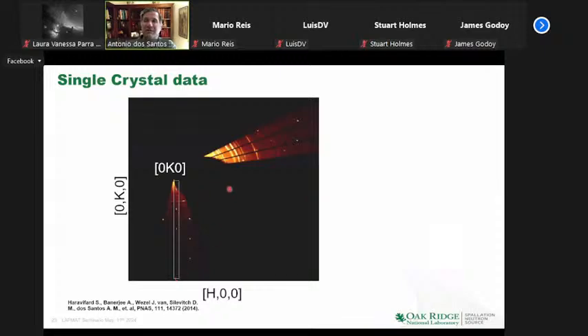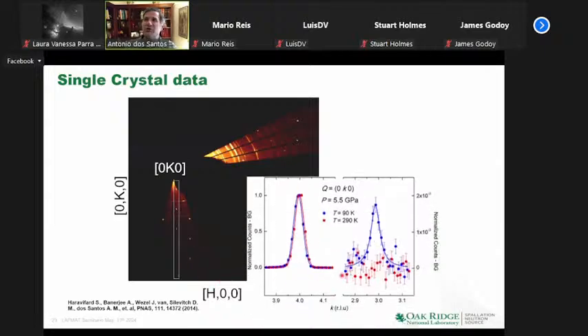Now, this pressure cell only allows in-plane scattering. So all you have is this HK plane, but you can see that in single crystal, every spot shows up and is resolved. And this is the advantage of time of flight neutrons: this is a single configuration of the instrument. There are no rotations, the cell is static, and you get all this information with two detectors. This is why Brugger was saying this time of flight technique is really compatible with the confined geometries of pressure cells.